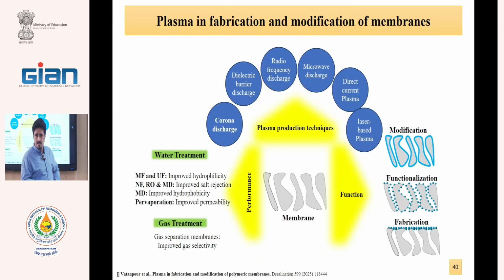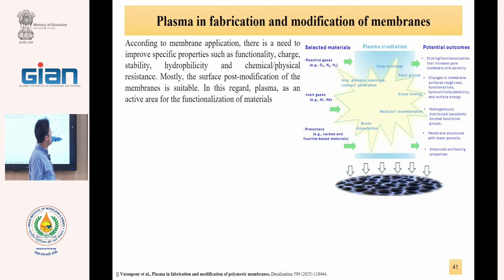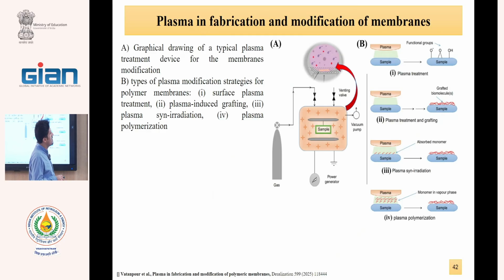Or using plasma in the fabrication of membranes, we have different types of plasma, and we can modify a polymeric layer on the support, or we can produce nanomaterials with plasma, or we can cause the grafting of some monomers, some polymers to the membrane surface with plasma. And you see here, as I said, with polyethylene, with plasma, we increase the hydrophilicity of the polyethylene. Also, we can increase the hydrophilicity of all polymers. We can increase it for polysulfone with cold plasma.